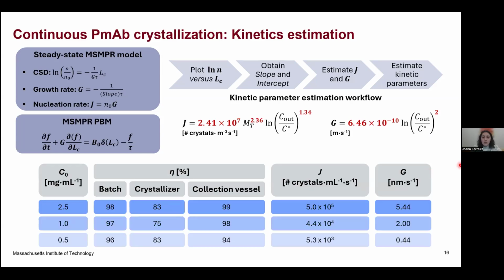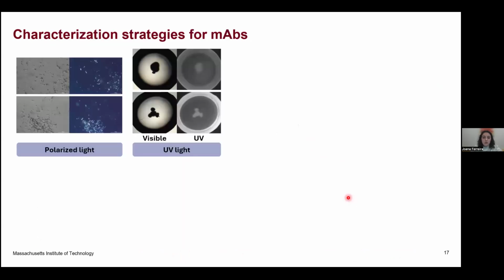And we did our first trials with the data collected during the continuous runs. So as you can see, we obtained very high yields for both the batch and the continuous runs. And then we could, from the simulations, we estimated the nucleation and the growth rates for the different runs. And it was interesting to see, because no values have been reported for monoclonal antibodies, but it was interesting to see that these values fall very well with what has been reported for model proteins such as lysozyme and insulin.